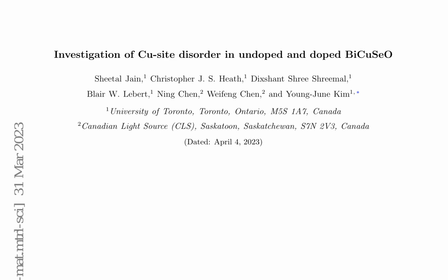Notably, the EXAFS data at 80 K were not usable due to higher noise levels caused by condensation effects at low temperatures. The fit results for the 3 samples at 150 K are also presented in the figure, with the fit ranges shown via the window function in solid green lines. The quality of the fits can be visually assessed by comparing the data and fit curves.